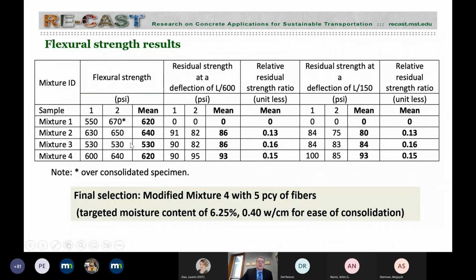So flexural strengths, the mean flexural strengths, 620, 640, drop to 530, and then increase to 620. And the residual values, if we were to look at L over 150, again, we were hoping to get 0.20, but the highest was 0.16. So given the consistency of the mixture and the mechanical properties, the decision was made to use the mixture that had 5 pounds per cubic yard. And this is the mixture that finally we used.